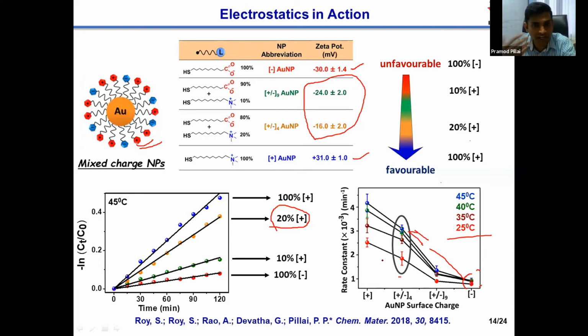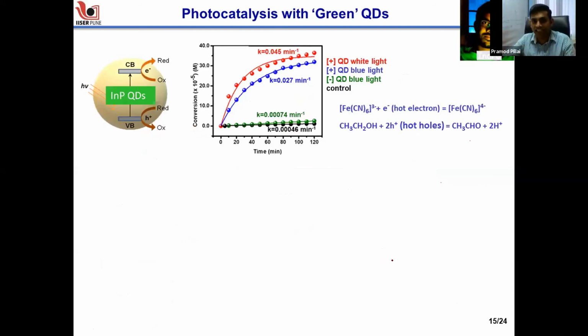So then, motivated by this, we have extended this to other nanoparticles as well. This is an example for semiconductor nanoparticles, which are called quantum dots. So here the electron transfer theory is a little different. We don't have hot electrons here. Rather, we have conduction band electrons and valence band holes, where upon photoexcitation, these conduction band electrons can be used for the reduction reaction, and the holes can be scavenged by a hole scavenger. So the same thing as in the plasmonic metal nanoparticle, but here we don't have any hot electrons. So here again we found that there is a strong effect of surface chemistry on the reduction of ferricyanide.